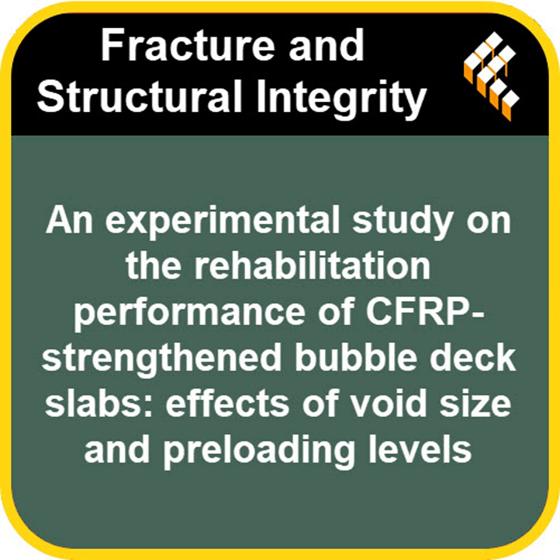Okay, here's where it gets really interesting for me. What happened when they applied the CFRP to those 50-millimeter void slabs, the Group 1 specimens? Did it actually make a difference? Did it bring them back? It made a significant difference, yes. After they applied the CFRP, their ultimate load capacity actually increased by somewhere between 1% and 4% compared to the original unreinforced bubble slab. Increased, so stronger than before they were damaged. Stronger than the undamaged bubble slab baseline, depending on the pre-damage level. And maybe even more impressively, the deflection at failure was reduced by up to 23%. Wow.